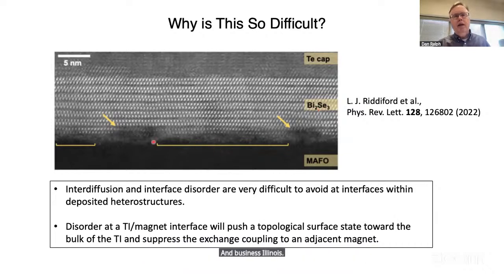And basically, it's very hard to grow very nice interfaces with these types of materials using deposition techniques like MBE. Interdiffusion and interface disorder is almost impossible to avoid. And this is a problem for trying to get strong exchange coupling between a surface state and a magnet, because any kind of disorder will push the topological surface state toward the bulk and away from an external magnet. The exchange interaction is sort of exponentially sensitive to that, and so you lose quickly if you start having disorder.